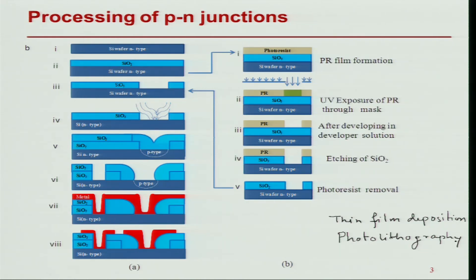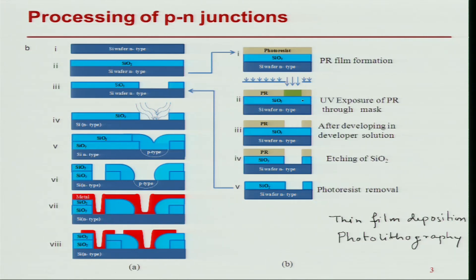What is this photolithography process? The first sub-process is we deposit a photoresist — in short form called P-R. This we can spin coat; it is a polymer in certain solvents and additives. After spin coating it, we normally pre-bake it to get a certain amount of hardness. Then we expose it to UV light coming through a mask. The portion where there is no mask, the light comes through; where there is a mask, the light will not come through. The property of this photoresist is chosen such that wherever the light has come through, its chemical properties have changed — that portion is exposed, and wherever the light is not, that portion is not exposed. After development in certain chemicals, the part which is exposed is removed. So I have taken a flat film and created a pattern in the P-R.